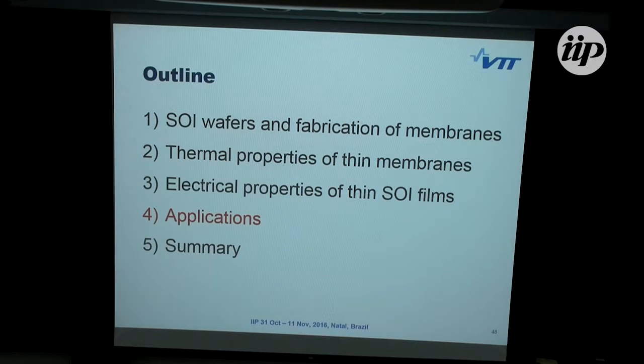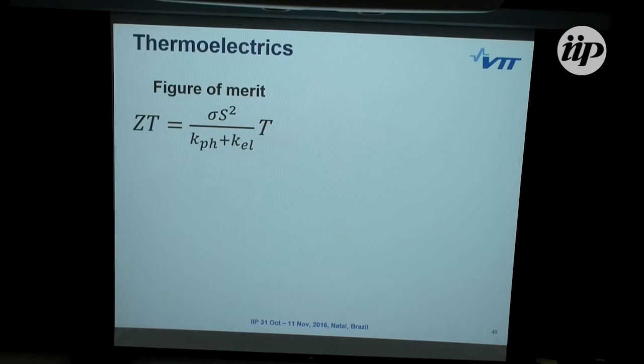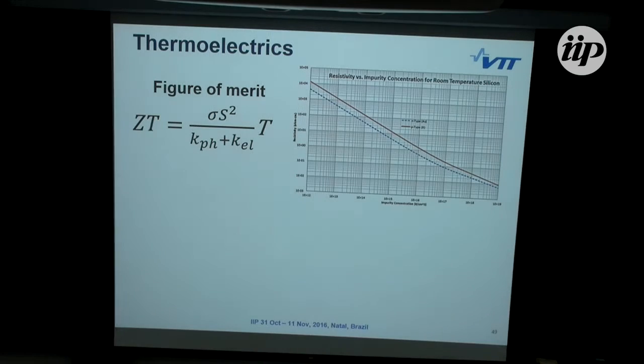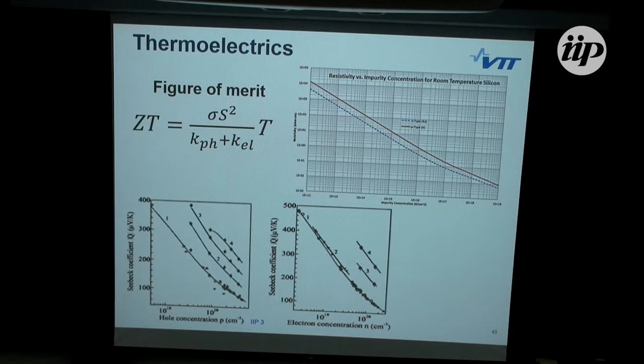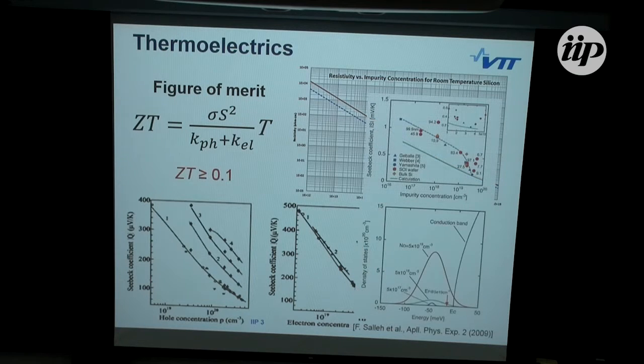So, a few words about applications. This was shown already by Davide. What we can play around with is, of course, the electrical conductivity, which can be tuned by doping, and the Seebeck coefficient. In the case of thermal conductivity, the electronic part doesn't play basically any role in semiconductors, so it's the phonon thermal conductivity.